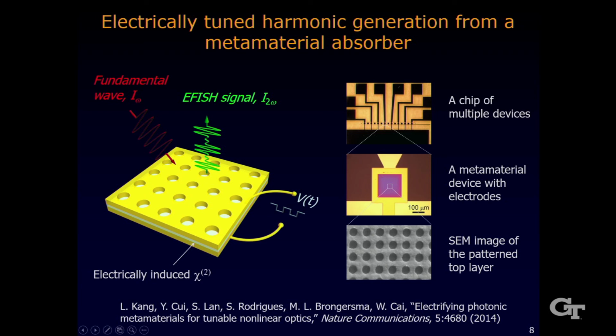Such a configuration gives rise to a number of important features that facilitate the so-called E-FISH, electric-field-induced harmonic generation of light. For example, this metallic structure simultaneously supports electrical and optical functions. This metamaterial absorber can suck light from the external world and focus light into the dielectric spacer, which is certainly good because for almost all nonlinear optical interactions, the efficiency is proportional to the intensity of light. Also, there's a nanoscale gap here. That means when you apply a certain voltage, there's an enormous static electric field in between.